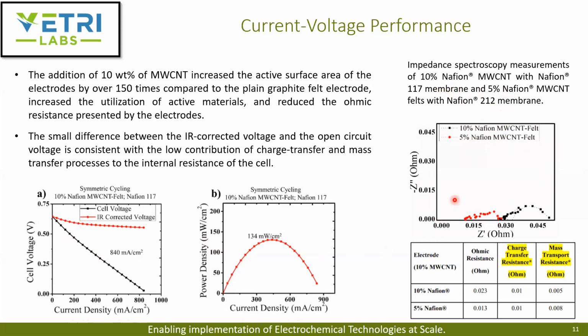charge transfer resistance decreases with increasing the current, and mass transfer resistance contributions do not manifest until the current approaches the limiting current for mass transport, while the ohmic resistance is expected to not change with the current. So as you can see, the overall decrease in the cell voltage is largely attributed to the ohmic loss. So they did the ohmic correction, and what you can identify is that there is a small difference between this IR corrected voltage and the open circuit voltage. This is consistent with the low contribution of the charge transfer and mass transfer process to the internal resistance of the cell. As we can see here, the ohmic resistance is higher when you use a 10% Nafion, and it decreases when you use a 5% Nafion.